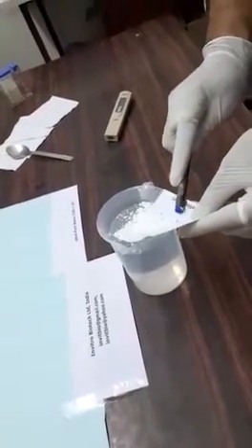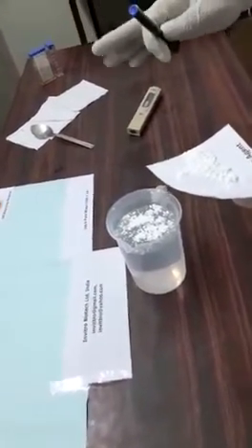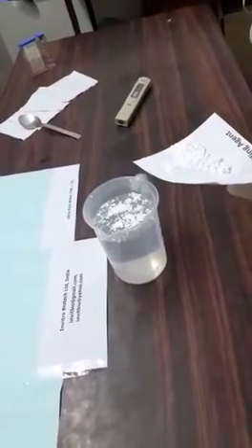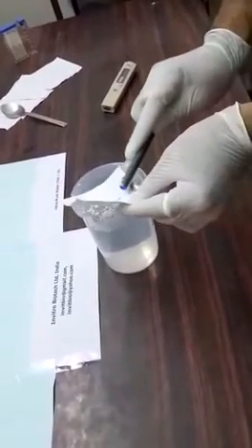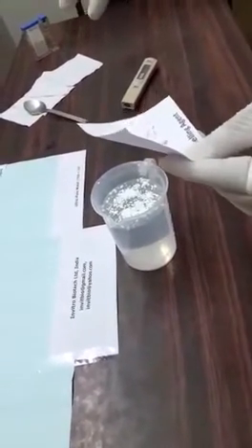Then do the fourth sprinkle — again wait for three to four minutes. In the video I am waiting only three to four seconds, but you have to wait for three to four minutes after each and every sprinkle. Remember, this powder is going to make about 500 ml of gel — half a kilogram of gel — but you have to take a very long time putting the gelling agent on the surface of water. The more time you take, the better your gel will be, because this is not easily soluble in water. It doesn't dissolve — it simply goes inside the water and expands. If you want your gel to be lump-free and smooth, please remember to take these precautions.